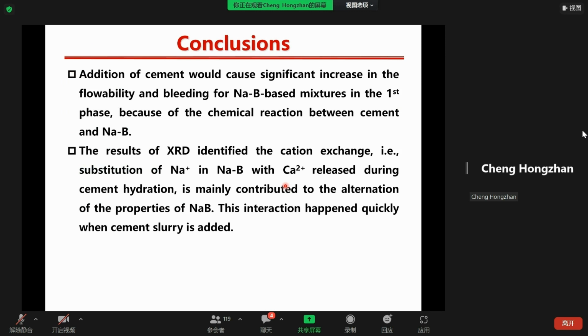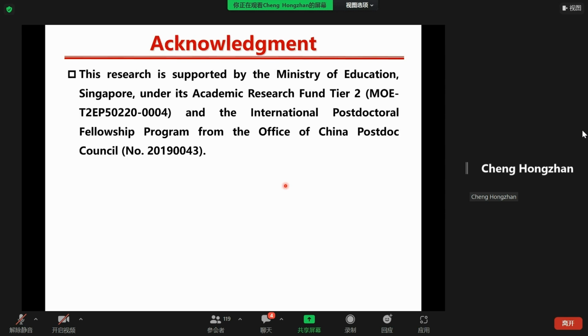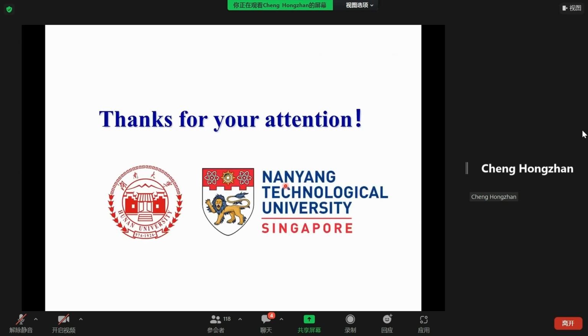Okay, last part is the two main conclusions in our studies. Addition of cement would cause a significant increase in the flowability and the bleeding for sodium bentonite based mixtures in the first phase because of the chemical reaction between cement and sodium bentonite, and the XRD results identified this cation exchange between them. Okay, finally, this study was under the support of the Ministry of Education in Singapore and the Chinese Postdoctoral Council. Okay, that's all. Thanks for your attention.